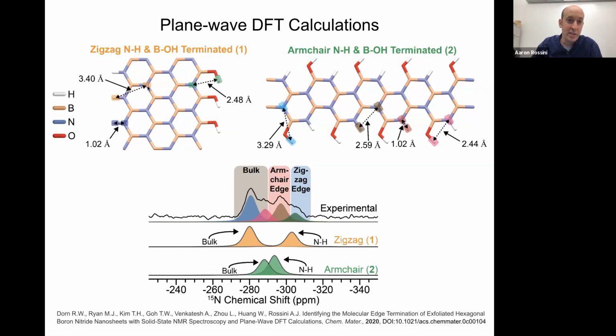So these are going to be the nitrogen atoms that are the first layer in from the surface. Those are going to show up here. And when we look at the edge groups, the amine groups on the edges, that's predicted to be this peak that we see here. For the armchair edge termination, we also get good agreement with the experiment.